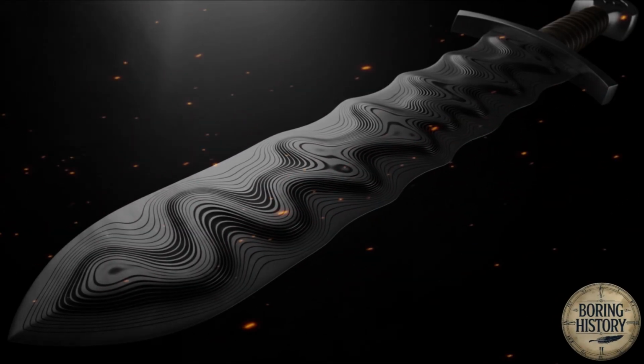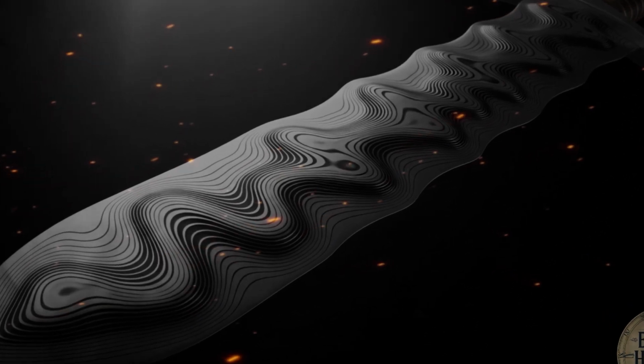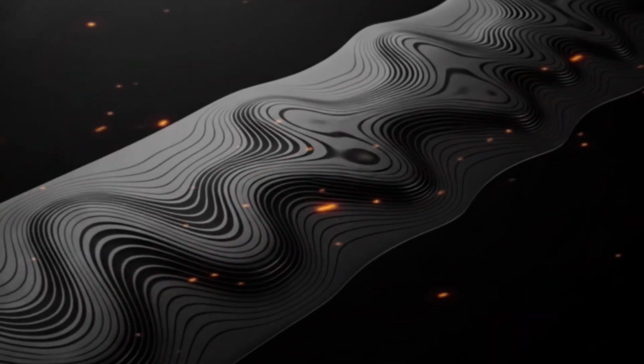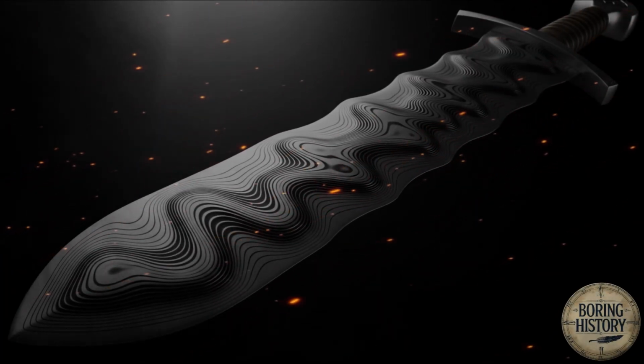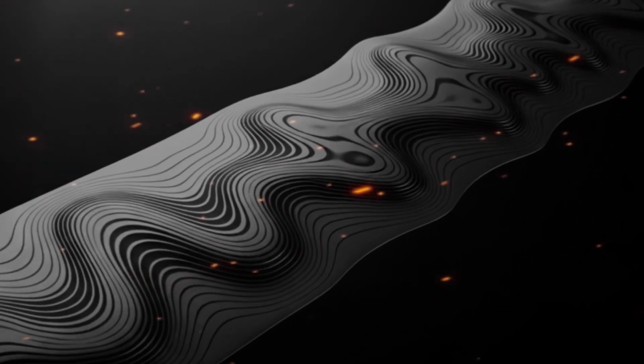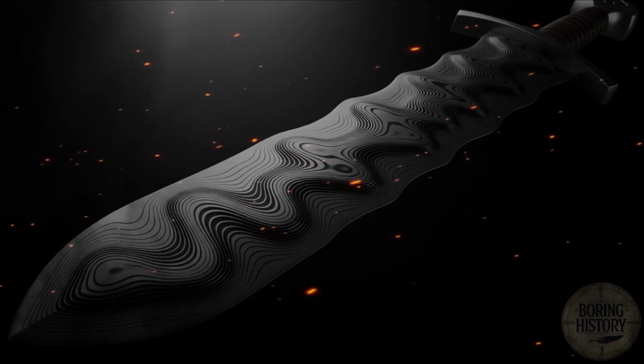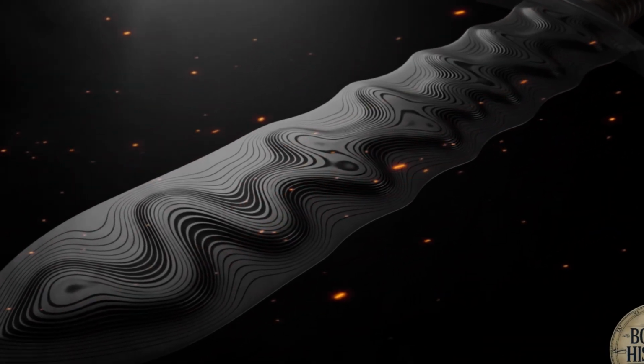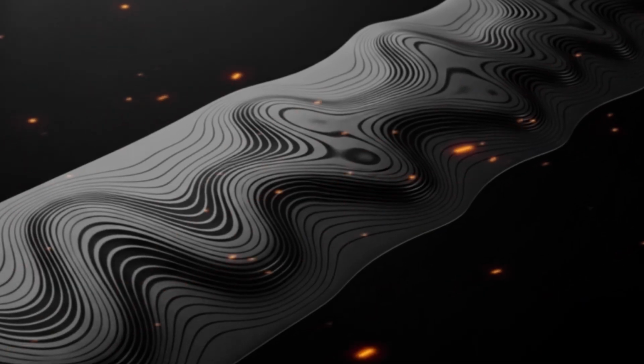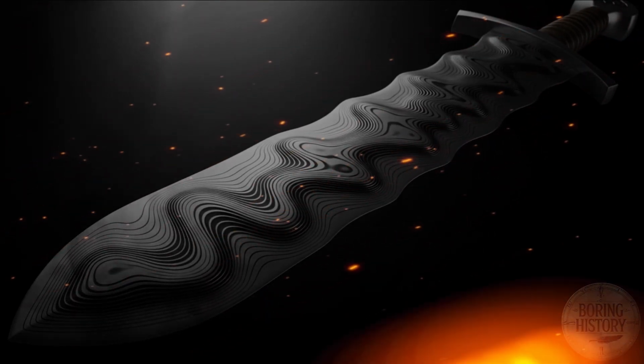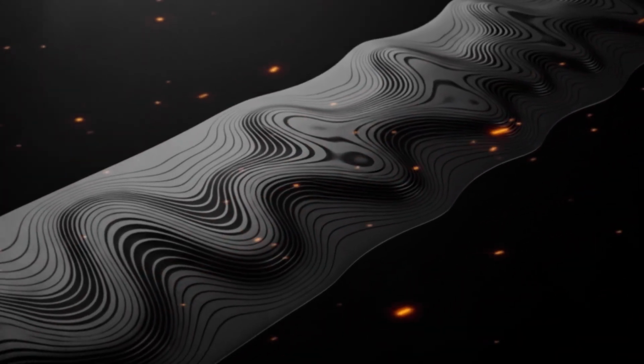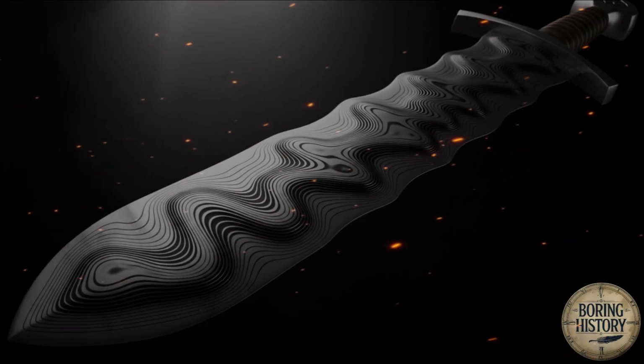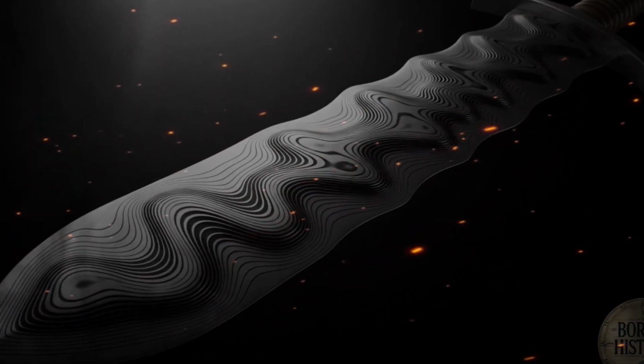The science behind it is this: steel at high temperature has a particular crystalline structure. The carbon atoms are dissolved into the iron lattice, evenly distributed, mobile. When the steel cools slowly, as it does when left to cool in air, the carbon has time to move, to migrate out of the lattice and form carbide compounds at the grain boundaries, and the result is steel that is tough and workable, but relatively soft.